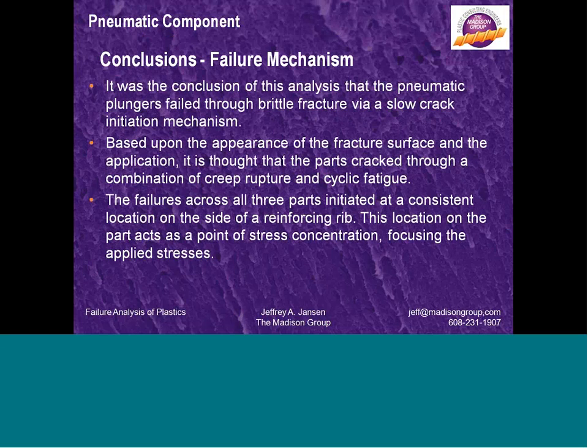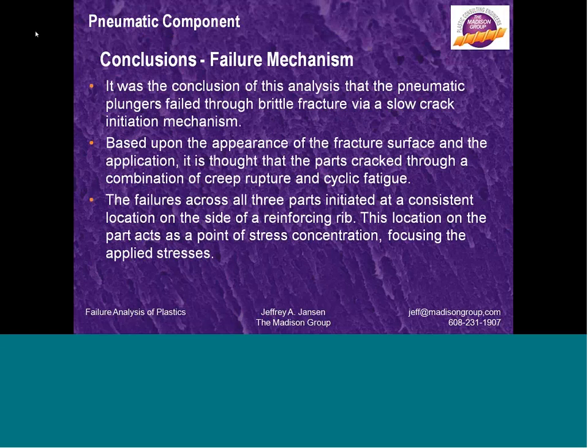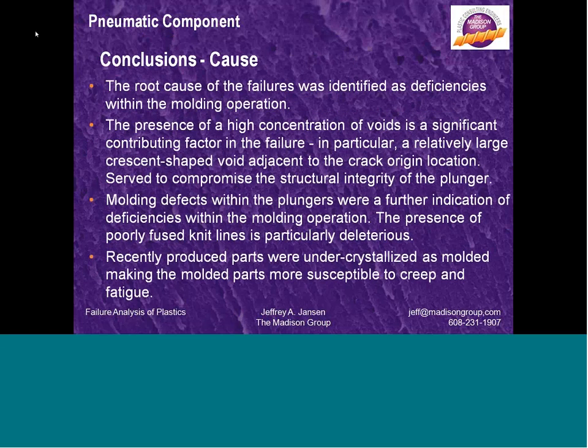The failure across all three parts initiated at a consistent location, an area which acts as a point of stress concentration, which focuses those applied stresses. The cause then was identified as deficiencies within the molding operation. The presence of a high concentration of voids, again, was a significant contributing factor as it loses integrity of the part.